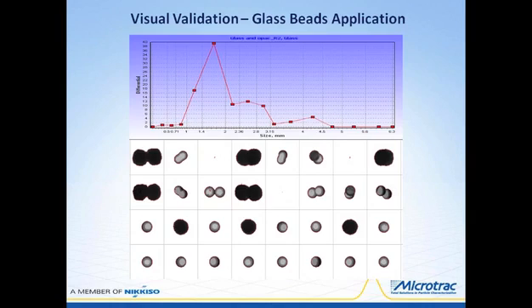This is a sample of reflective glass beads used in highway coatings, with some sand added for traction. In this small excerpt from the SI's image file, we can see good round transparent glass beads, bad fused glass beads, single black opaque particles and agglomerated opaque particles, both of which are sand grains. And the small chips in 3 spots are probably abraded from the bulk sample, showing in the fine end of the size range. This is a perfect example of how visual validation can answer questions about why the size distribution is shaped the way we see it.